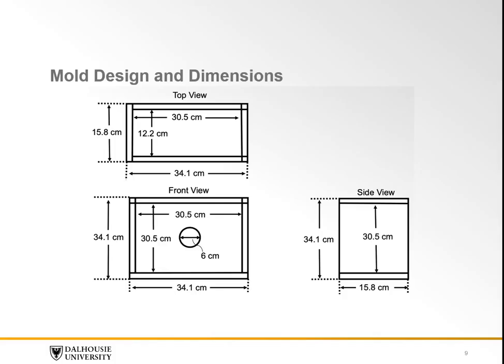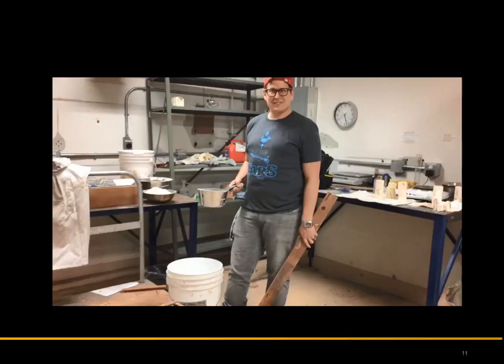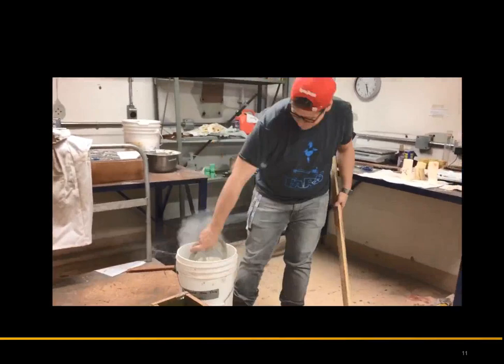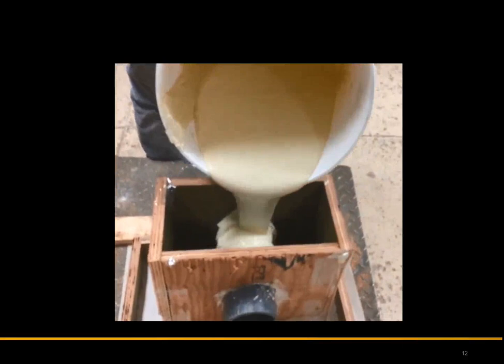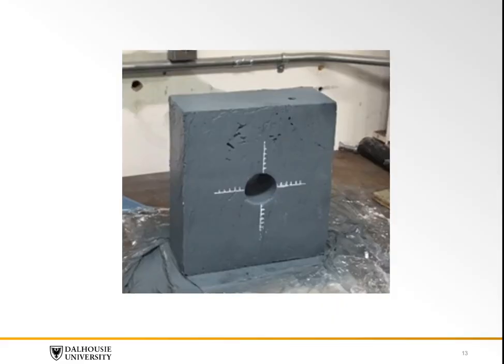The design for the mold was to have inner dimensions of 305 mm × 305 mm × 122 mm, with a 60 mm hole through the center to allow a piece of PVC pipe to be placed through. The mold was constructed with plywood and PVC pipe to create the excavation. Once the mold was created, the ingredients for the plaster were measured and combined to create a mixture with a consistency similar to pancake batter. Once mixed to a proper consistency, the paste was poured into the mold and leveled, then cured and loaded under the instrument press to induce spalling behavior.